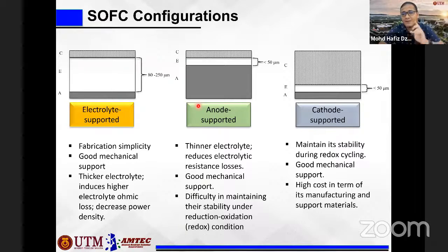So therefore, having the anode as the thickest part, we can actually reduce some costs for the electrolyte and cathode, because we use a very small amount of them. And also because of this anode support, it can reduce the ohmic resistance which comes from a thick electrolyte. If you have a thin electrolyte, you can reduce the ohmic resistance. Okay.